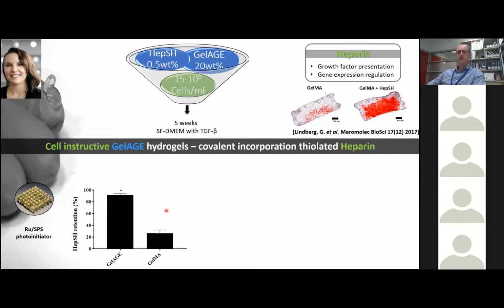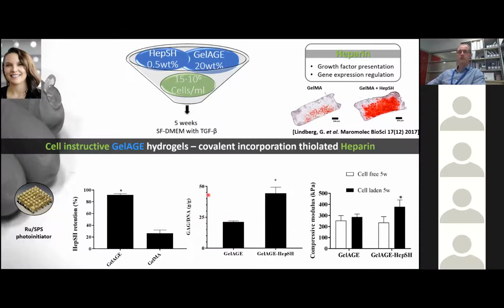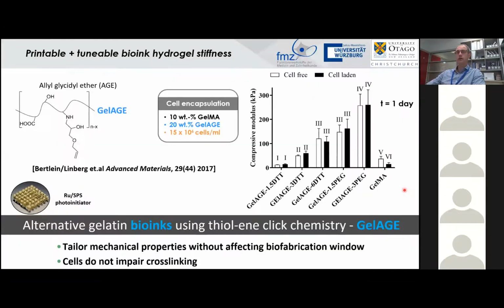Again, the step growth cross-linking process is very efficient with retention of thiolated heparin. The presence of heparin then meant that we could get enhanced tissue formation, and after longer term cultures, that then resulted in increased mechanical properties. So in terms of chondrogenic differentiation, this is an interesting bioink, which could control a cell instructive capability for cartilage tissue formation.